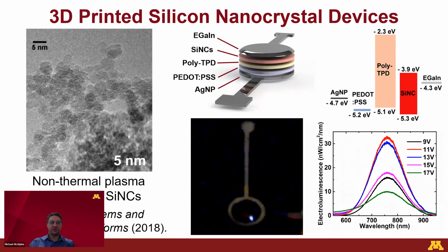Now, actually, we did that before we moved to University of Minnesota. Then when we moved here, we found out that Professor Kortshagen synthesizes these silicon nanocrystals using a plasma system. And now we can actually start to incorporate silicon into our 3D printing system. So silicon, as you know, is the mainstay of the semiconductor industry. That's why it's called Silicon Valley. So now we can actually introduce silicon into our 3D printer and have the world's first fully 3D printed silicon-based semiconducting device. And the beauty of these quantum dots is the fact that they are 5 nanometers and smaller, and what happens with silicon at that length scale is that silicon behaves more like a quantum material than it does a bulk material.